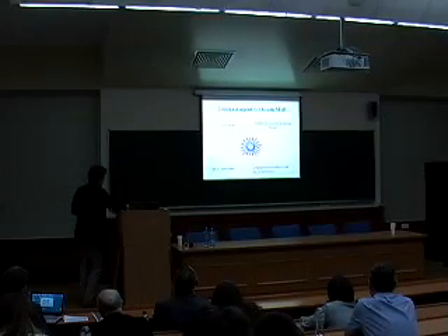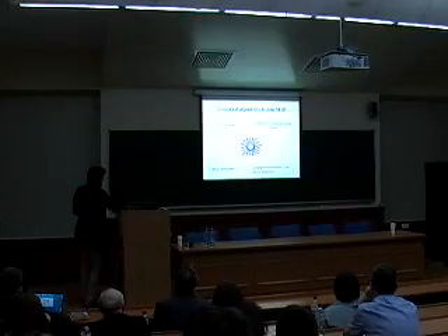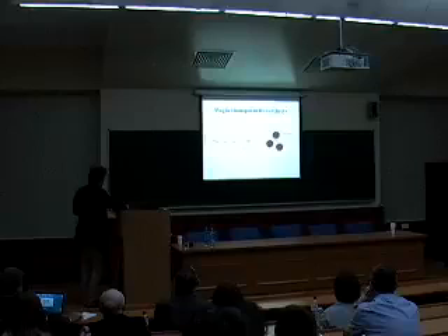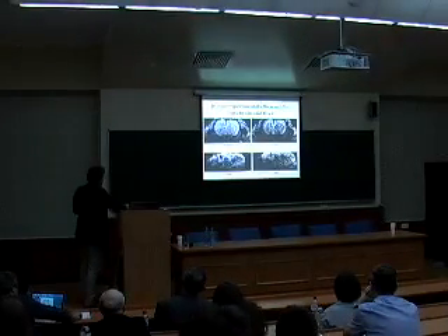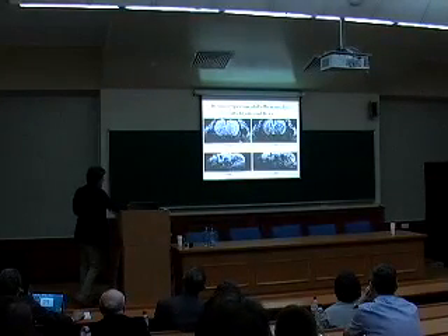So we have a lot of research work. Here's our cooperation with the Mendeleev Chemical Institute. We investigated such nanoparticles with some polymer coating. This part is iron oxide. So this is the chemical structure. The size of these particles is about 10 nanometers, and we succeeded in very good enhancement of contrast.